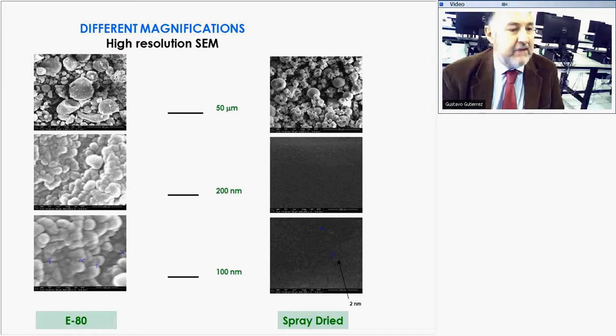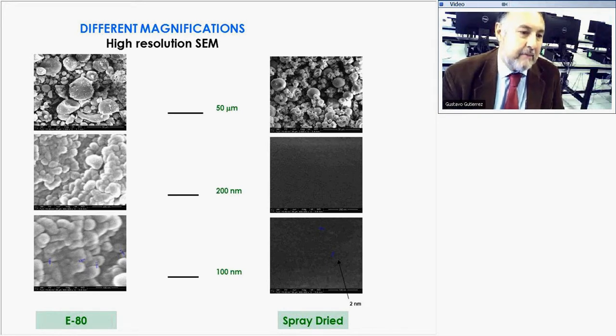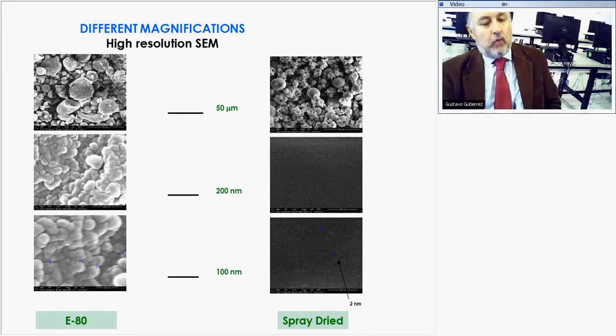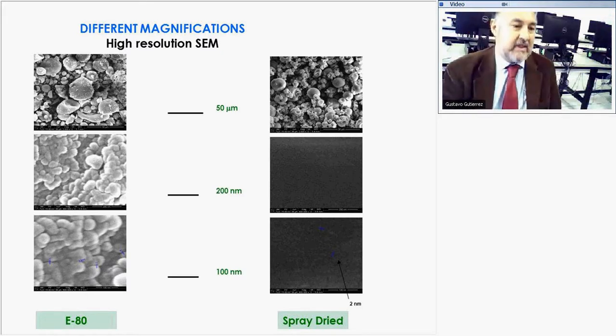These are different magnifications of the same material that we present here: 50 micrometers, 200 nanometers, and 100 nanometers. We can see that the detail of this structure here is much more complex than here. This is our E-80, and this is the spray dried. So what can we expect from this?